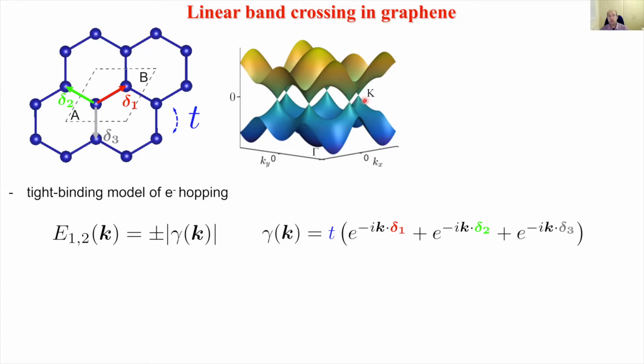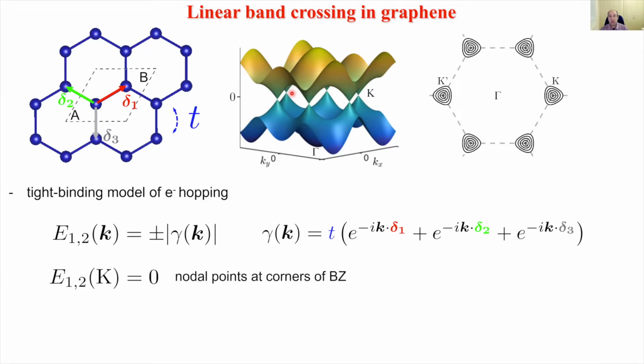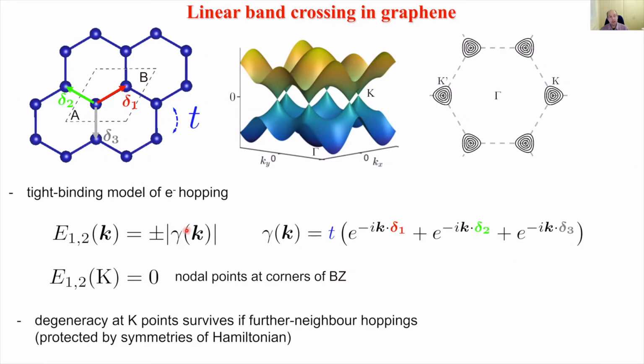at the corners of the hexagonal Brillouin zone, these 6 points indicated here. And at these positions, the energy is 0 in both cases, and this coincides also with the Fermi level of graphene at half filling. Now an important property here is that the degeneracy survives also if further neighbor hoppings are included, as it is a fundamental property of symmetry of the Hamiltonian on this lattice.